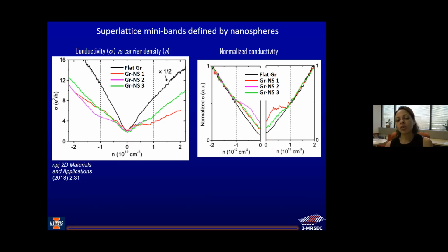So if you normalize the high density regions, you can see that all of the different slopes basically match up at high density, okay? And then all of a sudden you get to 1 × 10^12, and the flat graphene continues with no change in slope. And the graphene on the nanospheres all has a jump. And that's both on the hole side and on the electron side, you get this jump at 1 × 10^12, okay? But why is 1 × 10^12 important?